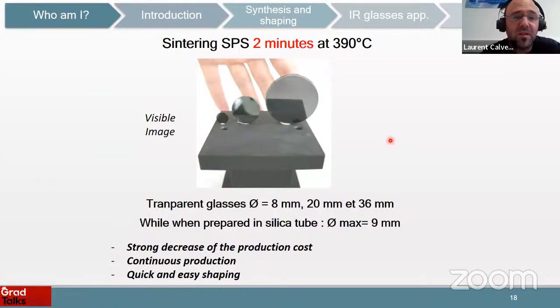Because it's very efficient. The sintering step lasts only 2 minutes at 390 degrees C instead of 900 degrees C for 12 hours. And also, what is interesting here, for this kind of composition, we have diameters of 8, 20, and 36 millimeters. While when you use silica tubes, the maximum that we can achieve is 9 millimeters, because after that we get a crystal inside instead of a glass. So there is a strong decrease of the production cost, but also now we are able to work this way using continuous production, and it's quick and easy shaping.